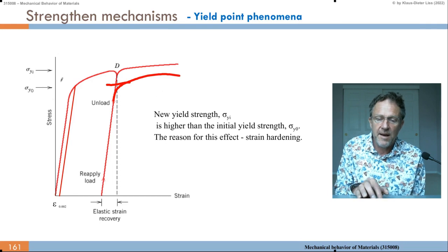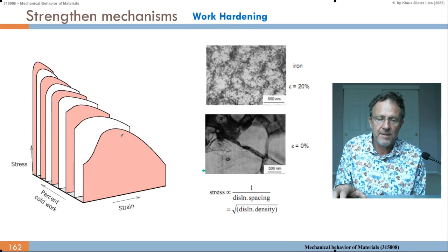So after each cycle, it becomes harder and harder and harder. That we see here, the work hardening. We call that work hardening. When we work the material, it hardens. So the first curve may be like this, elastic, and then we get plastic deformation here. We get the UTS and then it becomes weaker. So here we get work hardening and then UTS.